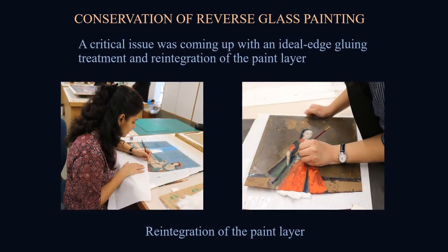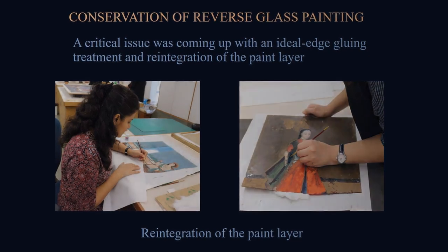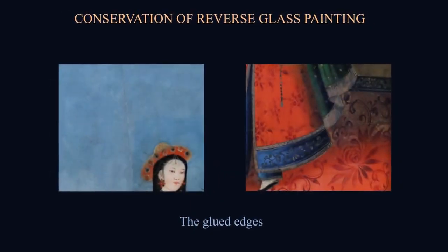A critical issue was coming up with an ideal edge gluing treatment and reintegration of the paint layer. Before joining the broken edges, reintegration of the paint layer was carried out for easy handling. The smaller areas were retouched directly on the reverse side of the glass to match the surrounding areas, and the larger areas were reproduced on an acid-free handmade sheet. After reintegration of the paint layer, the broken edges of the paintings were aligned properly and were glued using low viscosity, fast drying epoxy resin.